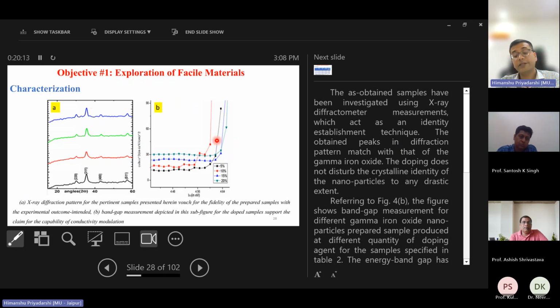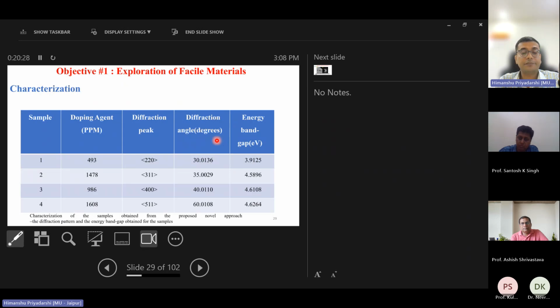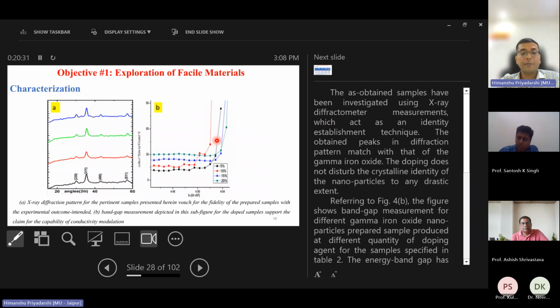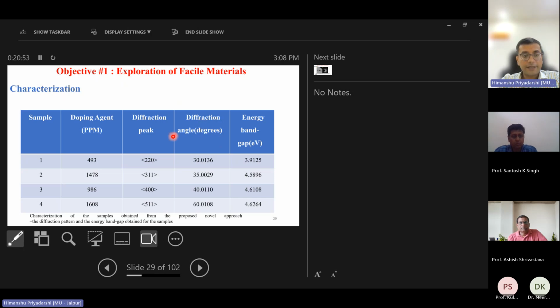For example, if we go to the introductory slide where I was referring to that schematic of the battery, even the active material of the electrode contributes to the resistance when it is connected to the grid. So all these parameters have to be considered. After all, what is resistance? Resistance, as a lumped circuit parameter, we say is resistivity times length upon area. But what is resistivity? Resistivity depends upon the mobility of the carriers, and other microscopic parameters. So if we see the band gap for the first sample, we obtained a band gap of 3.91, which is nearly two times in comparison to the bulk sample.